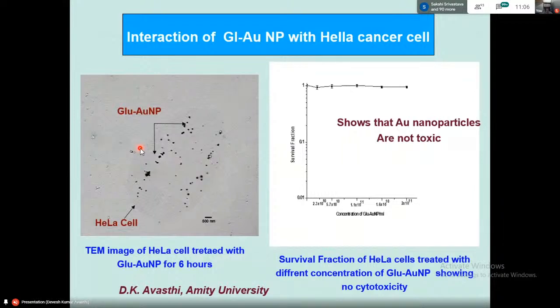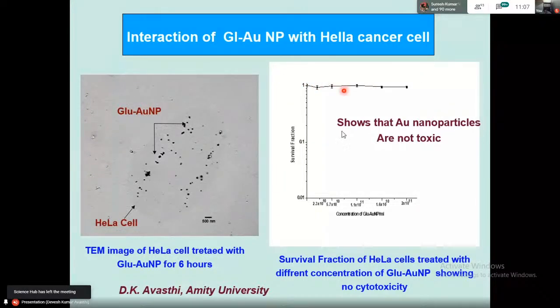With this reference, I wanted to show some experiments on the interaction of glucose-capped gold nanoparticles with HeLa cancer cells, a particular type of cancer cell. This is the cancer cell which you see here, and the black dots are the gold nanoparticles. This is a survival function. Different concentrations of gold nanoparticles are put with the cells in culture, and we see that the cells are still surviving. One means 100% survival, so this is the survival fraction. No matter how much concentration, they are surviving 100%. That means gold as such does not cause death to the cells, so they are not toxic at all.